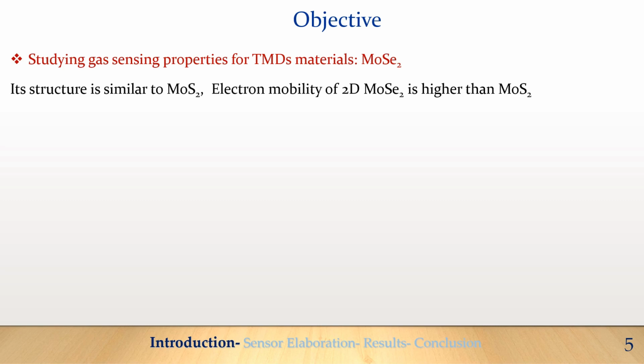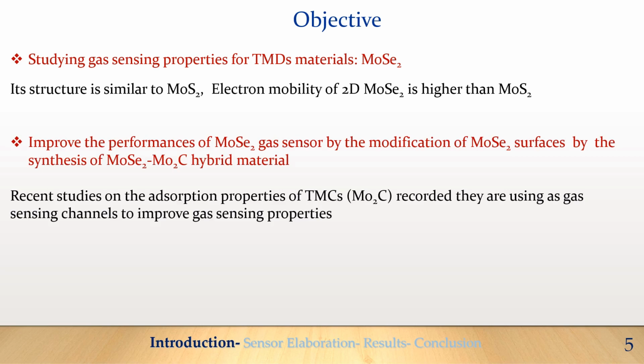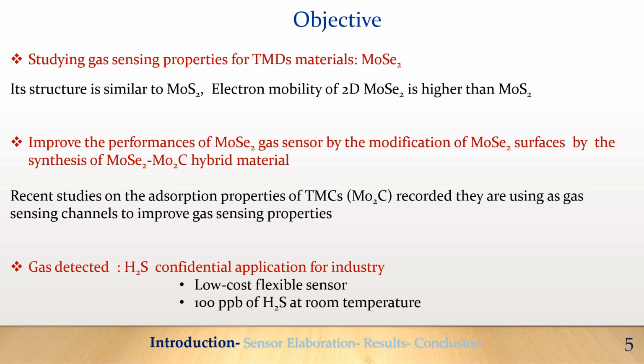In this research, the main objective is to study gas sensing properties for TMD materials like MoSe2. In fact, its structure is similar to MoS2 and the electron mobility of 2D MoSe2 is higher than MoS2. To improve the performance of the MoSe2 gas sensor, its surface is modified by the synthesis of MoSe2-Mo2C hybrid material. The choice is based on recent studies on the adsorption properties of transition metal carbides, where they are used as gas sensing channels to improve gas sensing properties. The gas detected for this project is hydrogen sulfide. An industrial application requires a low-cost flexible sensor able to detect 100 ppb of hydrogen sulfide at room temperature.